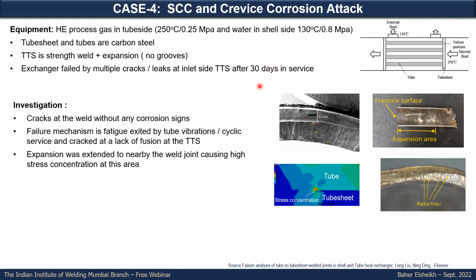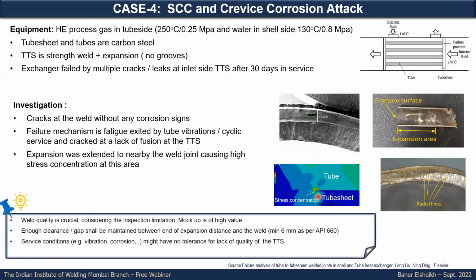And in such a very short time, there is definitely some contribution from cyclic service or vibration in the bundle itself causing this attack. That's why weld quality is very crucial. Inspection techniques are somewhat limited, especially for the weld pass, so mock-up is very important to ensure the quality of the joint. You should also have enough clearance between the expanded part and the tube-to-tube sheet weld, so that you will not affect the weld by cracking or having high residual stresses or stress concentration in this area. And based on the service, you have to mitigate the vibration, which is mainly part of the thermal and performance design.